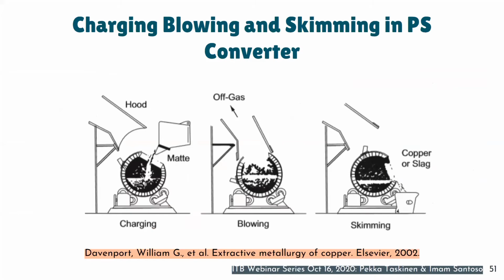And then this is the process of matte converting using a Peirce-Smith converter that the operator undertakes in a control room. First, the matte is charged to the Peirce-Smith converter. The converter is a bit tilted, and after that, we introduce oxygen, the blowing process. And when slag is formed and the iron is already removed, then we skim that slag. Basically, these are the three main processes the operator undertakes: charging, blowing, and skimming.